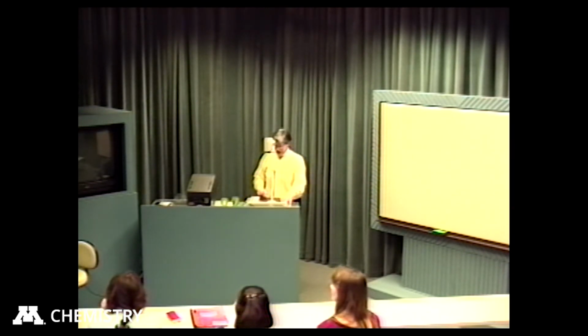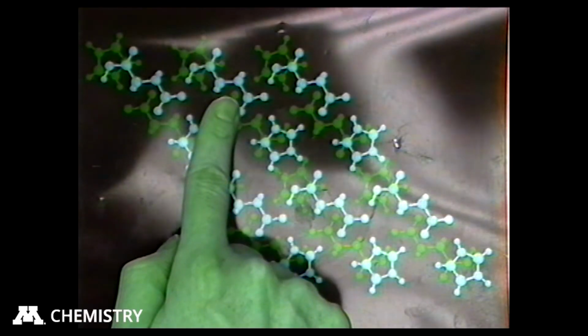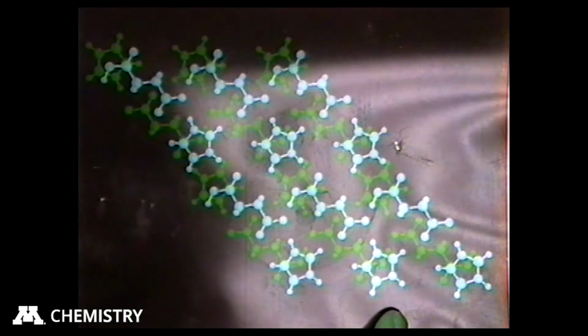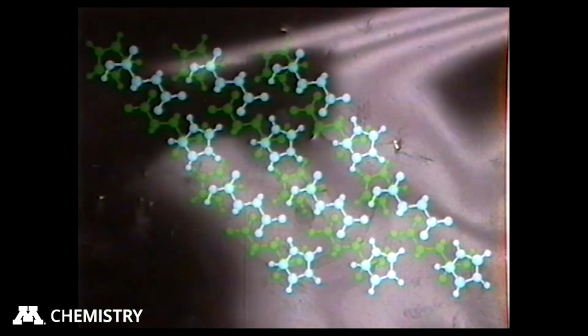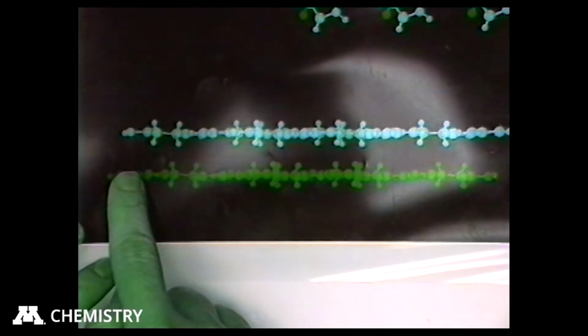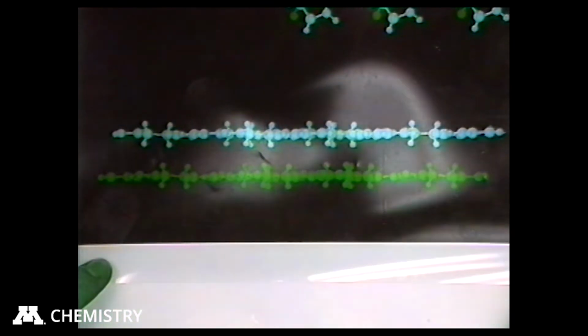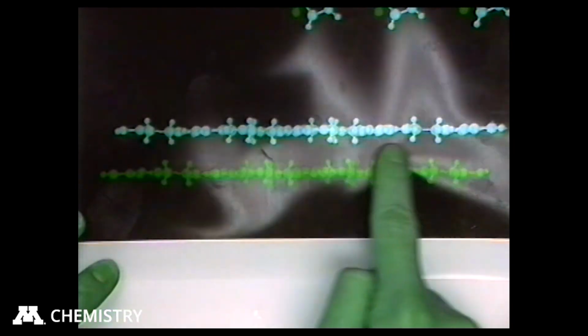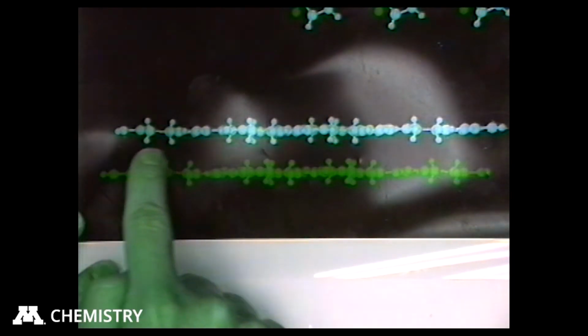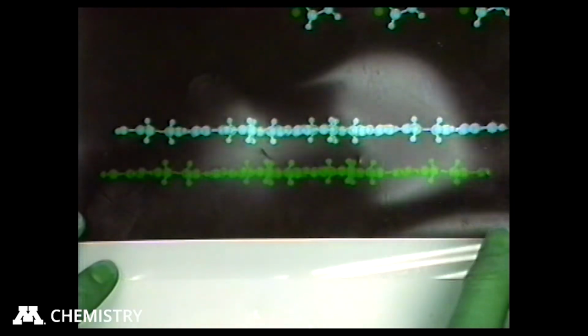All right, I'll show you at the top first a layer of the imidazole and succinate molecules alternating along a line here. And if you look at the crystal structure in another direction, 90 degrees to that, you see that these sheets of hydrogen bonded molecules are lined up just like sheets of graphite. And so there is a natural fracture plane along there. And so the crystals will cut very easily in that direction.